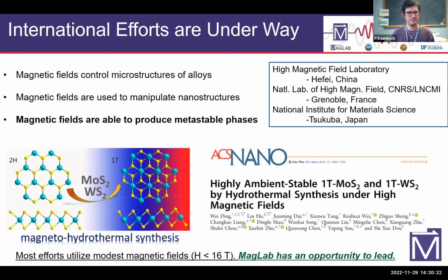And one that I think is especially intriguing is that magnetic fields can be used to produce metastable phases, metastable structural phases. That's shown in this publication that's at the bottom of the page here, where an investigation was made of some dichalcogenides, like molybdenum disulfide and tungsten disulfide, where hydrothermal synthesis was undertaken under varying fields. The main outcome of this paper is that if you do this in molybdenum disulfide or tungsten disulfide,